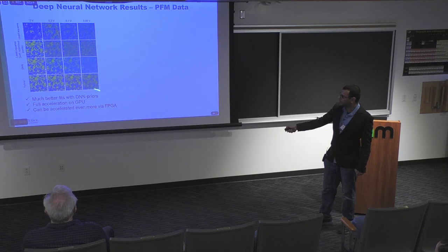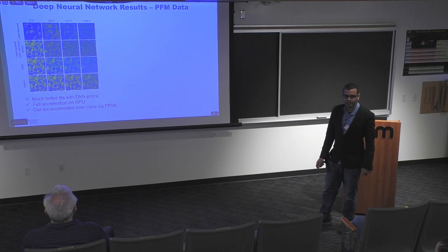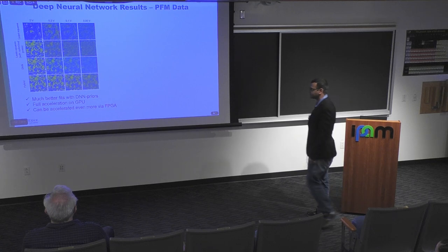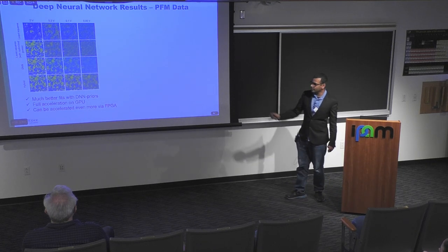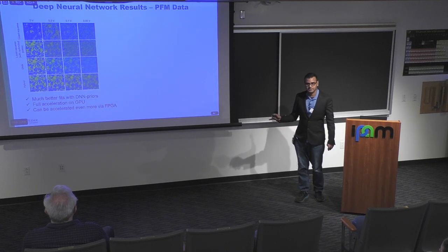And so what we find is that we have much better fitting of our spectra through these deep neural net priors. We can accelerate this even more through FPGA devices, so that you can actually incorporate the neural net on an FPGA and get fits as we stream the data. This is work that's being done right now by Josh Agar and Nan Tran and some of my colleagues.